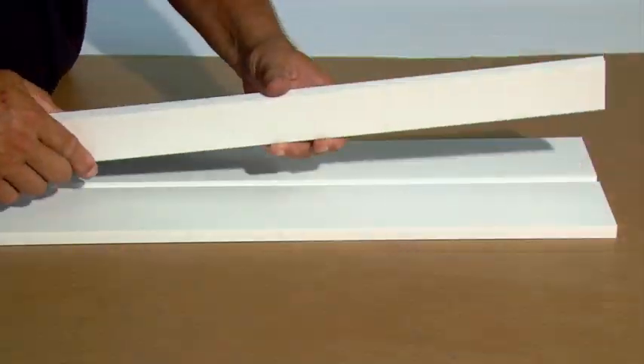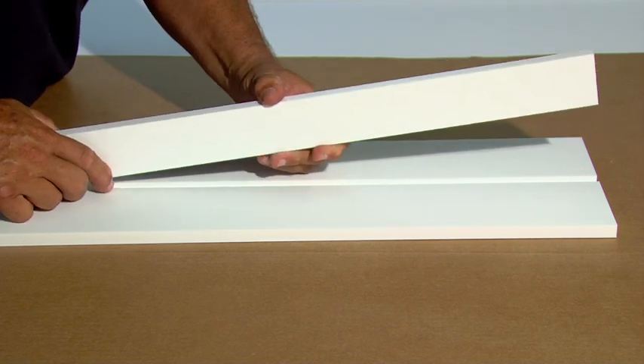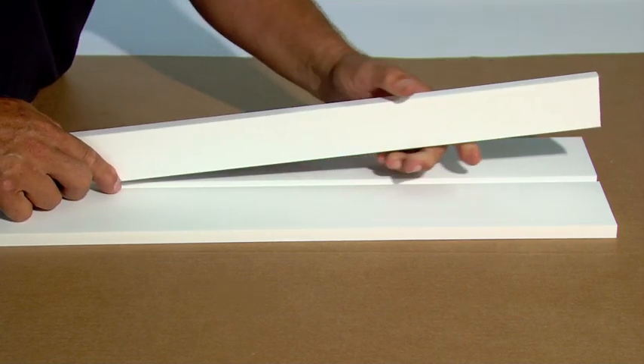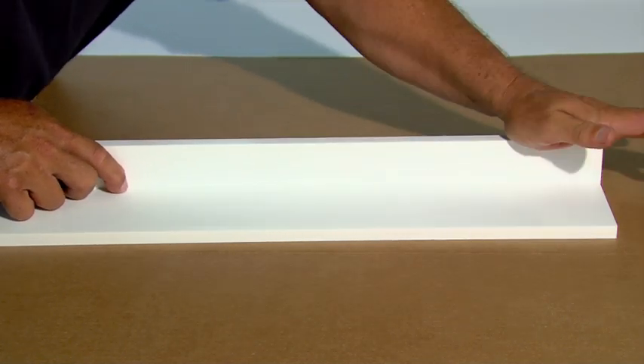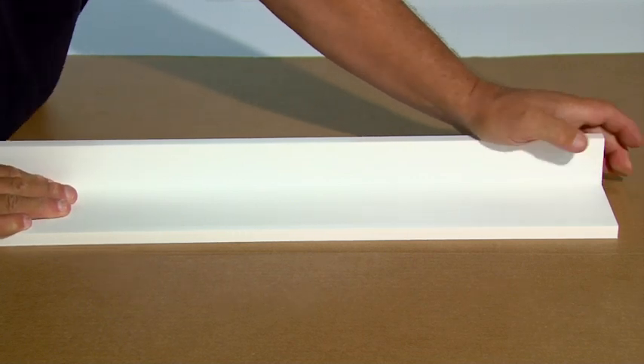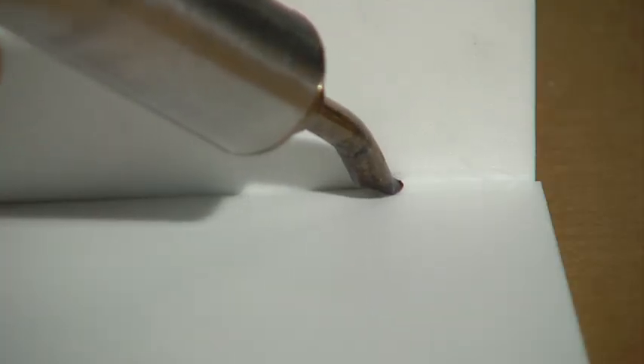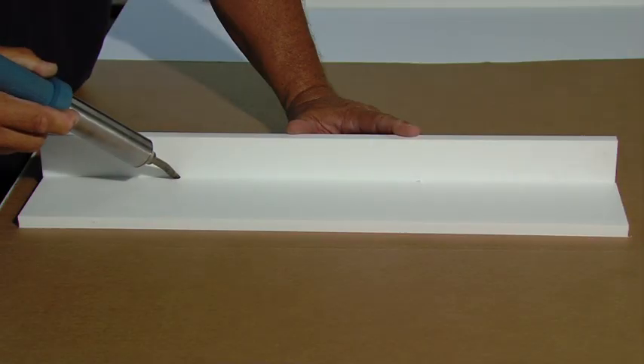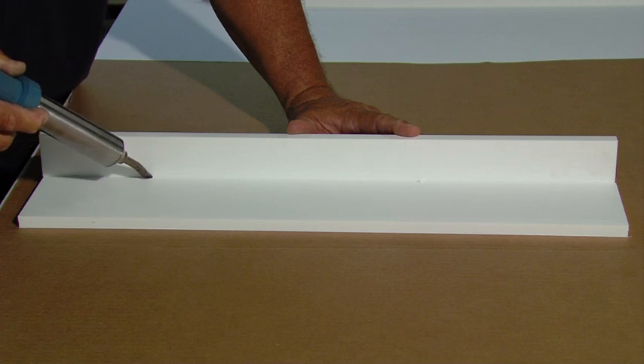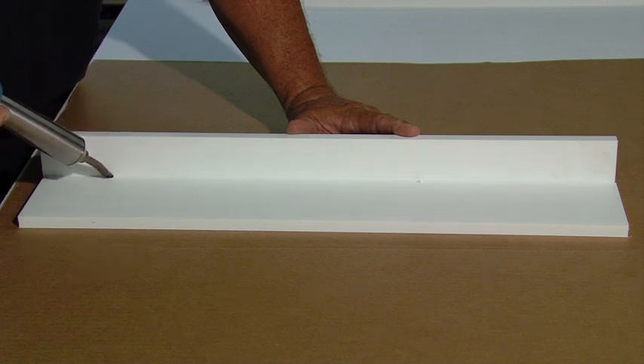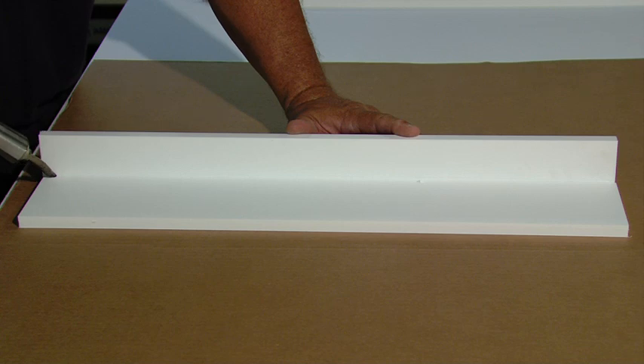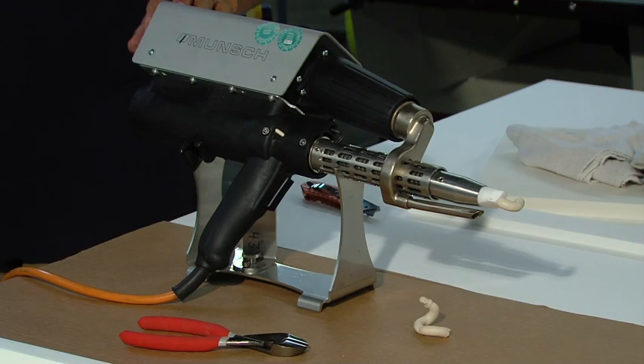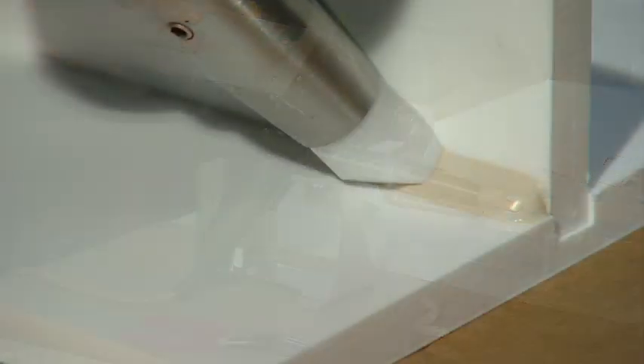For the most secure bond between two pieces of material, it is a good idea to first make a butt joint. Then, tack welds are produced when the hot tool is run along the seam where the two pieces of King Starboard ST are touching, producing a thin film of polyethylene joining the two pieces together. Tack welding is not strong and is used primarily for positioning to allow another fabrication method to be used.